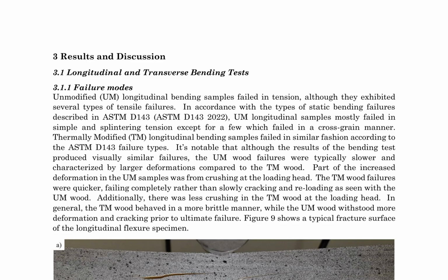Results from longitudinal and transverse bending tests on thermally modified, TM, and unmodified wood samples are presented. Longitudinal bending tests revealed that unmodified samples failed in tension, exhibiting simple and splintering tension failures, as well as cross-grain failures. In contrast, TM samples failed in a more brittle manner, with less deformation and crushing at the loading head. Figure 9 shows typical fracture surfaces of longitudinal flexure specimens.